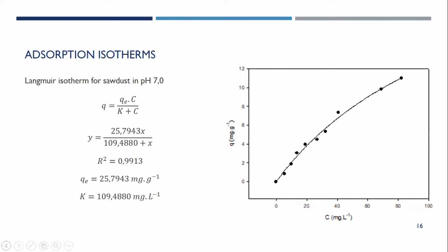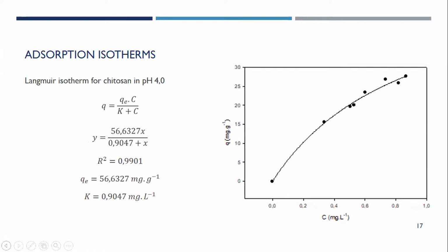At pH 4, the Langmuir isotherm for Chitosan shows an adsorptive capacity of 56.6327 milligrams per gram and a balance constant of 0.9047. Being lower than 1, these constant values show that the adsorption rate is higher than the desorption rate, indicating an advantage in the decrease of pH for Chitosan.